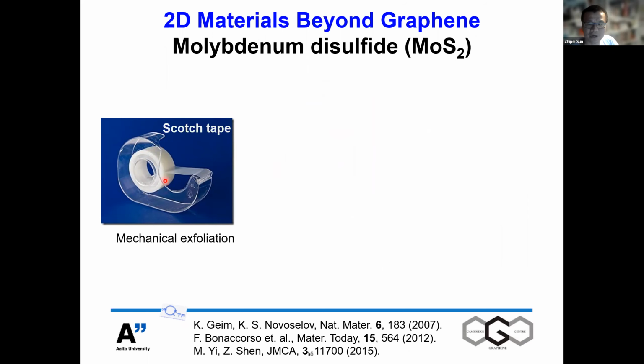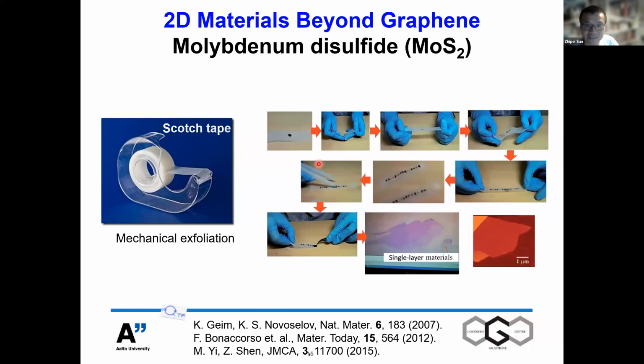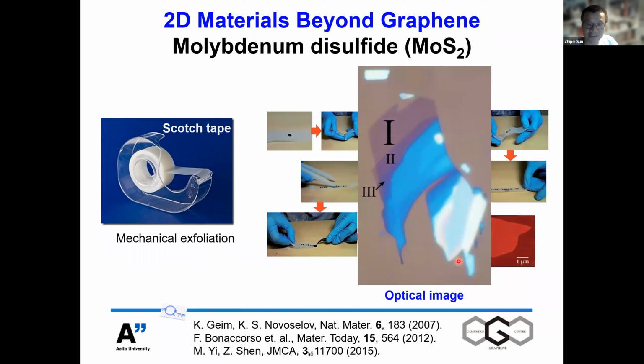Here we tried MoS2 beyond graphene. We fabricate the devices with the most famous mechanical exfoliation method. We started with a very thick bulk crystal, and then we fold the tape and press them, and then we fold them again, and then we unfold them again. Then we are able to get monolayer materials, for example, as shown here. This is a zoomed picture of the flake we get. You can see here we get monolayer MoS2. This is a bilayer area, and this small part here is also monolayer. This is a tri-layer, and this is a somewhat thicker layer sample.